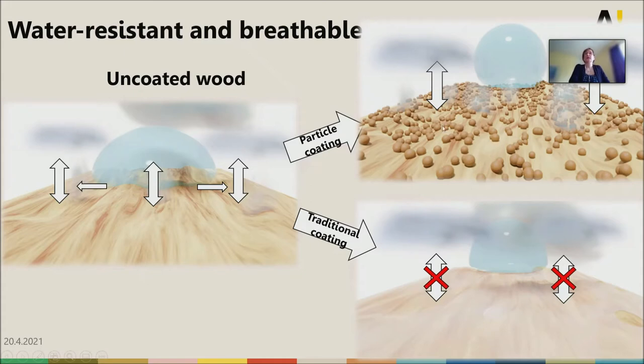With the particulate coating, we can still have the vapor go through because we are using such a thin layer. This is a big difference to many other coatings: we can use quite a thin layer, but we also get quite good hydrophobicity. So it's protecting from water. And if we compare this to the wax particles, this one is also covalently bound, so it's much more resistant to solvents and also mechanically quite strong. We have tested the mechanical strength of this.